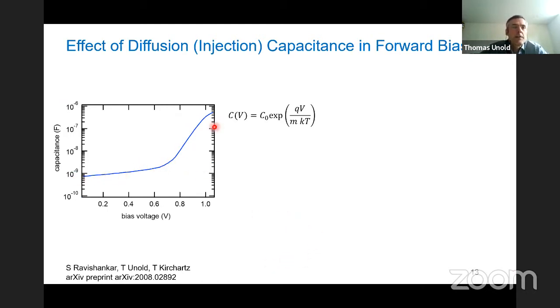So that's shown here. That's actually a simulation also with SCAPS in forward bias. And you can see that you can describe the capacitance in forward bias, at some point at least, with basically exponential functions, right? It follows the JV curve. So we have something like a diode factor in there and qV over kT, the exponential of it. And now you could say, okay, let's take this capacitance, do these formulas again, I do the derivative and so on, as I would do for a normal silicon solar cell. And then what you end up with is this equation here.